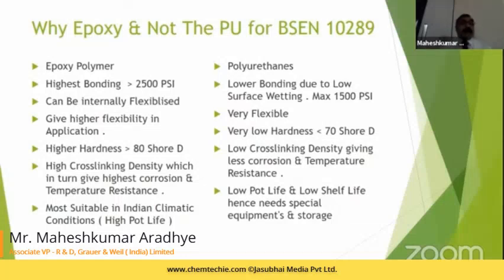You can have greater flexibility in application. You can apply it by brush, by single-leg airless, or by plural component. You have a lot of choice. You get a hardness above 80 for sure. You get a very high cross-linking density, which in turn gives you very high corrosion resistance as well as temperature resistance. In the case of polyurethanes, the cross-linking density is very low, and that's the reason it fails as the temperature increases.